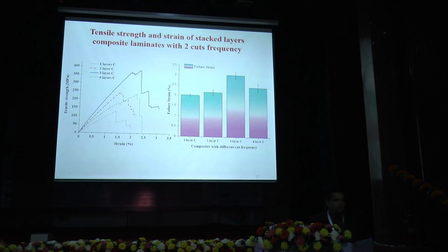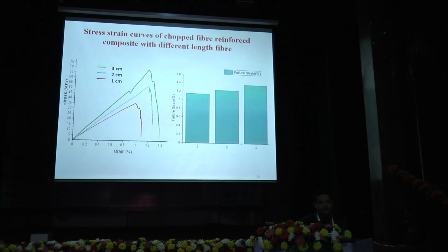The behavior changes from single fracture to multiple fractures, and the ductility percentage increases up to layer 3, then in layer 4 it reduces again, but it is still higher than layer 1 and layer 2. We have also seen the effect of fiber length on ductility.